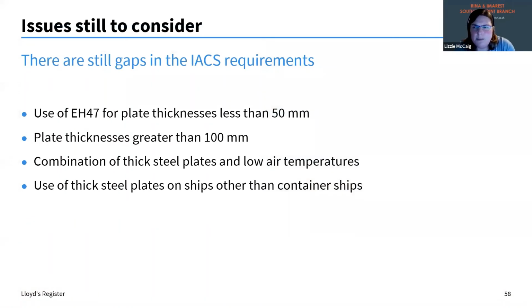There are, however, still some gaps. So, for example, in the IACS requirements, there's no mention of what you do if your plate thickness is less than 50 millimeters for EH47, and it's not mentioned in any of the other standards. And the reason for this is until fairly recently, no one's really using it for that. So no one's really testing how it can be used. But as ships get more and more optimized, you can predict that at some point someone's going to want to use EH47 for thinner plates.